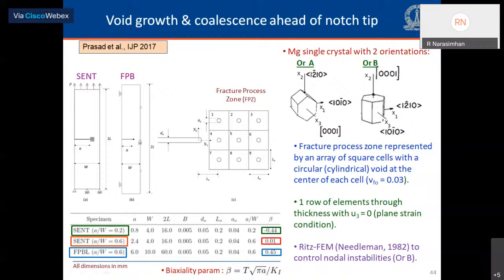And one of the features of our modeling is that we incorporate a set of voided cells, an array of square voided cells in the fracture process zone ahead of the tip, so that we can look at how void evolution takes place in the FPZ in the simulation. These are square cells with each cell having a circular void at its center.